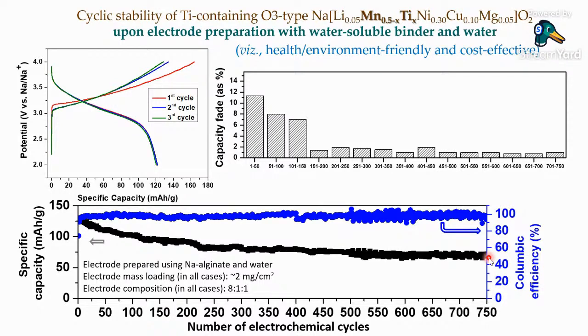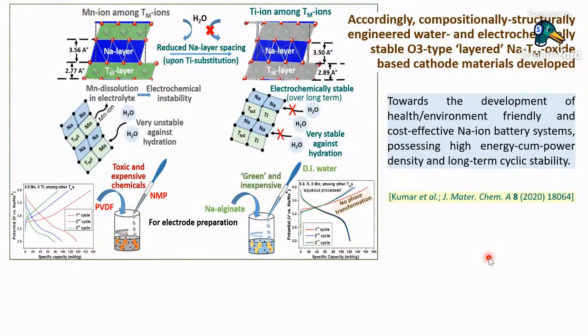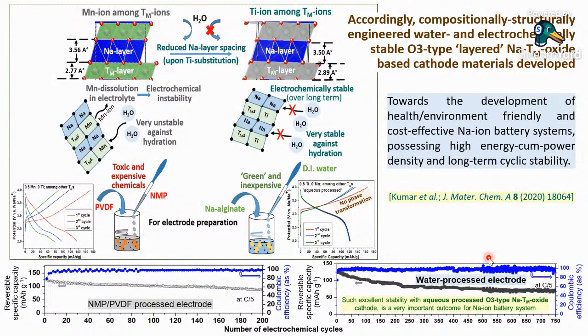So this is an important development because one has obtained a sodium transition metal oxide based cathode material which is very stable in air. So no need to run to a dry room or humidity controlled atmosphere for synthesis and handling of this material. And one can even prepare the cathode using a water based slurry and have a stable sodium ion cell cathode. So this is the summary of that particular work.